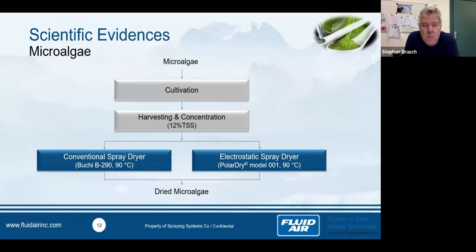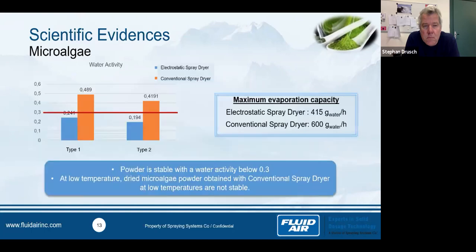This study was done with the University of Nantes. They gave us microalgae concentrated at 12%, and we decided to dry it at 90 degrees C at the same time with a conventional spray dryer, a bulky one, and an electrostatic spray dryer, which is Polar Dry. So the first result that I show you is that we wanted to check the water activity with a target below 0.3. And you can see that with an electrostatic spray dryer, it was possible to obtain this target compared with a conventional spray dryer.